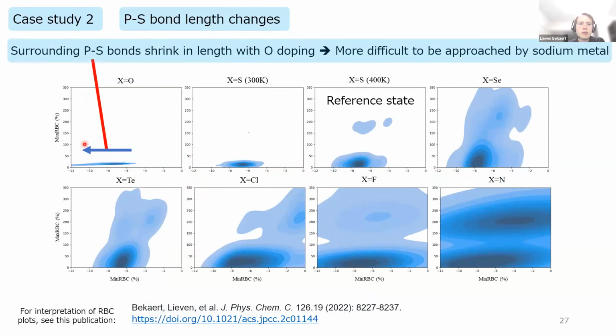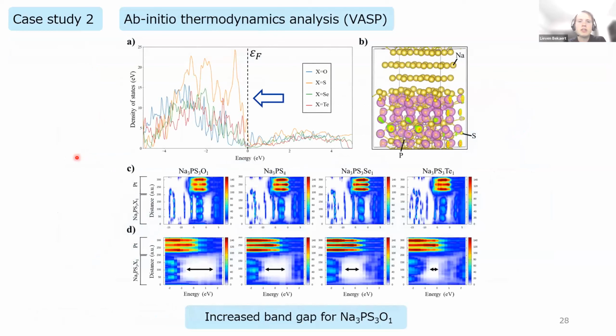Here's another way of visualizing what happens. So in one of our previous papers, we introduced this RBC technique, which is just another way of looking at how bond length, in this case PS bonds, changes in function of different element doping. And you can see that essentially the more color you have, the higher you go in value, the greater the bond length increases when you have, for example, elements which have either a lower electronegativity or elements which are unstable and will spontaneously react. And you can see compared to the reference state, so compared to the Na3PS4 pristine material, in the case of oxygen, there's a decrease in the bond length of these PS bonds. So a shorter PS bond, which means that sodium atoms cannot as easily attack this bond and react, and therefore explaining its higher stability. And once again, it's important to confirm with other methods. And in this case, we also performed ab initio calculations.